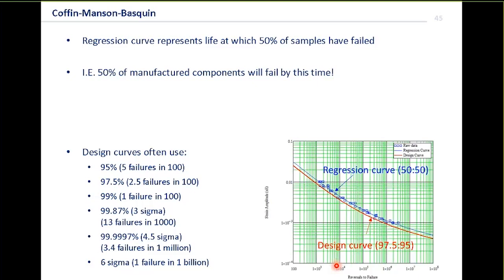So if we went for, say, a 95% reliability curve, that means we're getting 5 failures in 100. If we went for something like 99.9997%, then that's about 4.5 sigma, that's 3.4 failures in 1,000,000, and so on. And 6 sigma would manifest itself into about 1 failure in 1 billion. Now, it's worth pointing out at this point that most people, when they're looking at a design curve, typically look at something like a 97.5% design curve, or 95% actually as well.